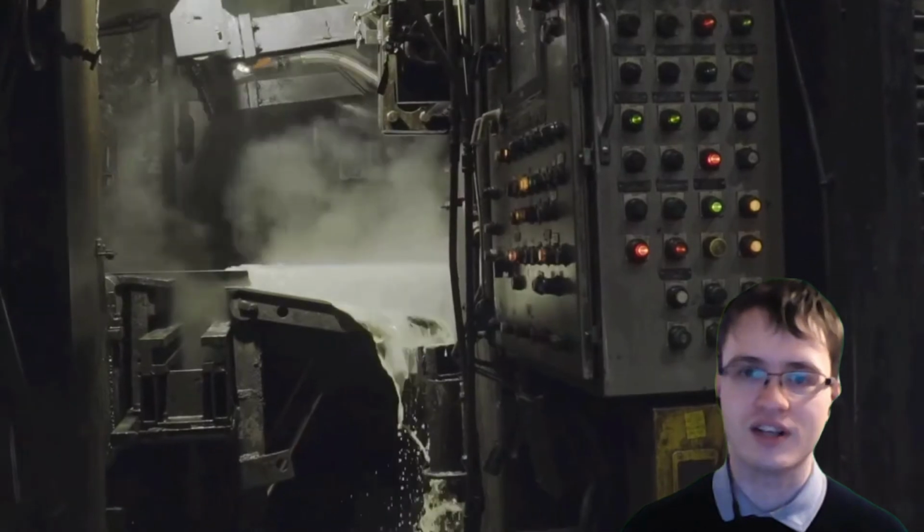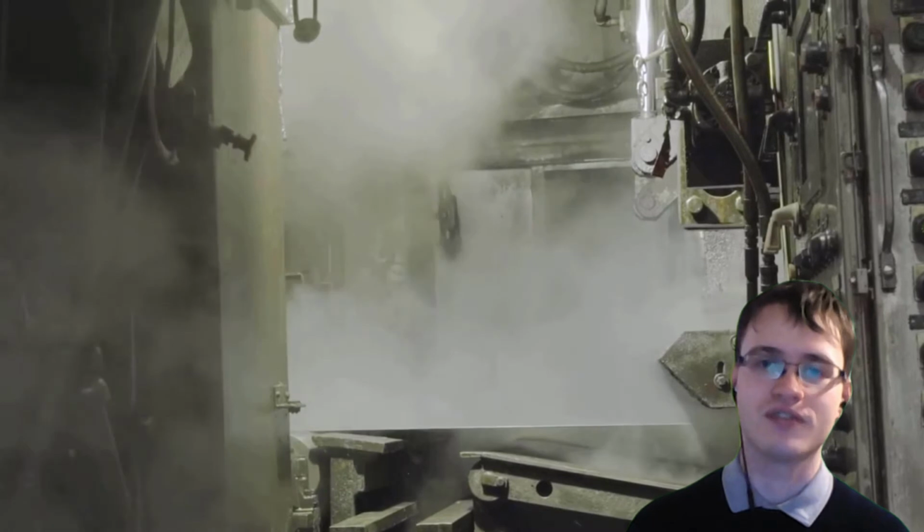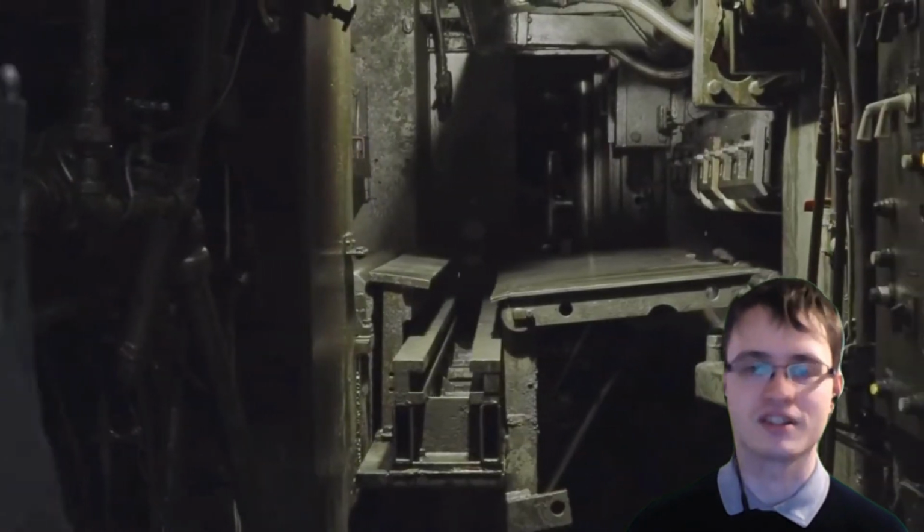By combining these two phases in differing amounts, we can create a composite material with a wide range of possible mechanical properties. We vary the ratio of phases by changing the furnace temperature and line speed, and said ratio of phases then dictates the mechanical properties of the steel.